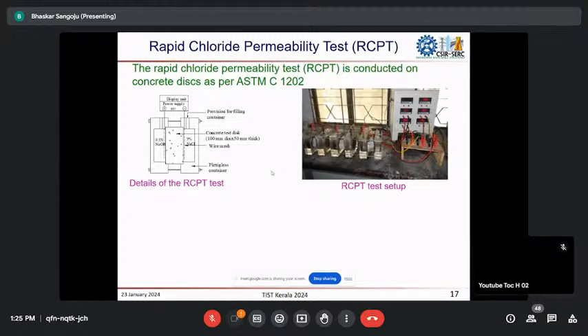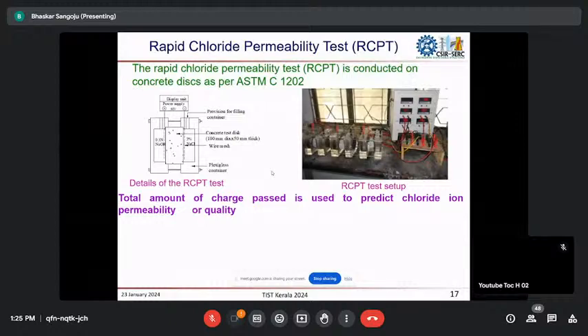So this is the RCPT test setup. The total amount of charge passed is used to predict the chloride ion permeability. The title says it is chloride ion permeability, but in concrete, because it is an accelerated test and we are impressing a 60-volt current, sometimes the solution may get heated and the specimen also may get heated.